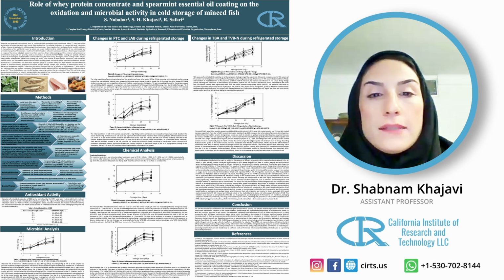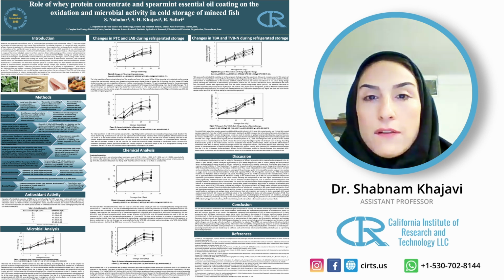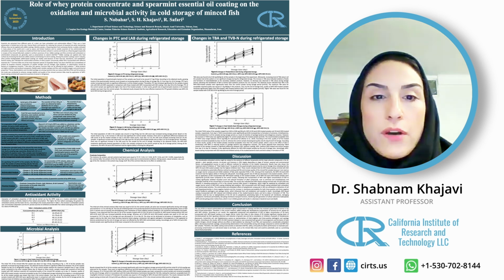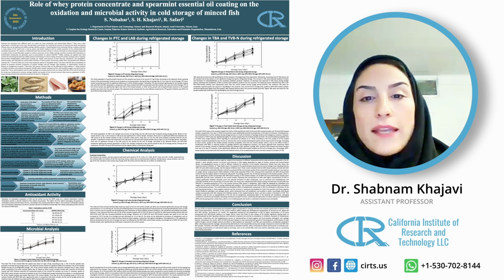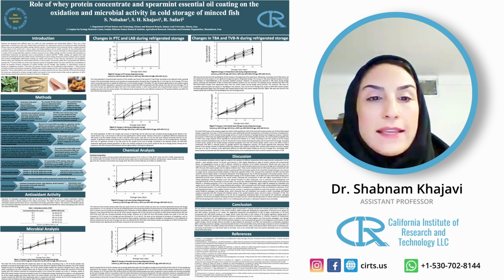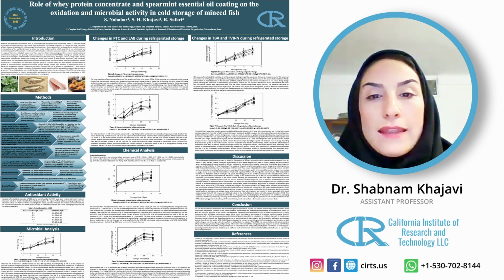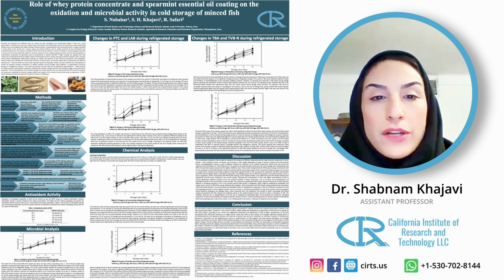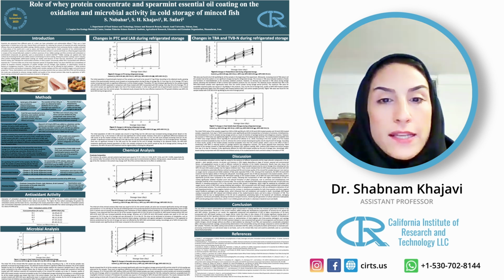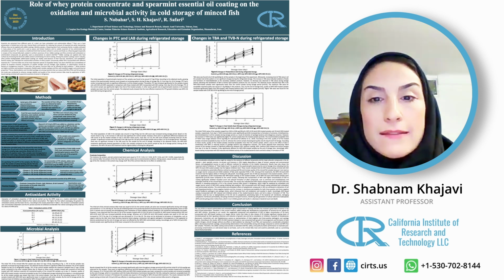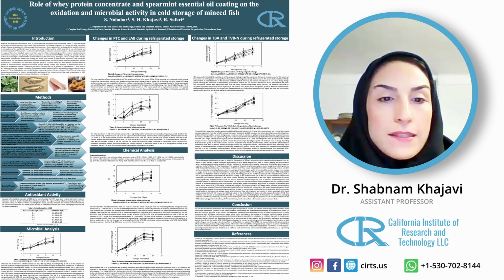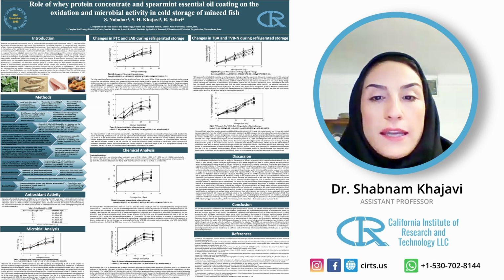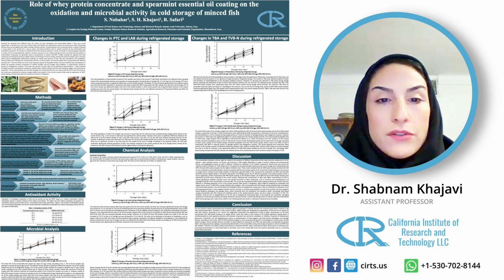According to our results, the oxygenated compounds and polyphenols of spearmint essential oil at the higher concentration of 1% weight per volume, incorporated with the whey protein-based coating as an oxygen barrier matrix that helps slow release of the essential oil, showed significant slowing down of microbial growth by lag phase extension and reduction of growth rate, and led to retardation or inhibition of growth of Pseudomonas fluorescens, Escherichia coli, and Staphylococcus aureus as representatives of gram-negative and gram-positive pathogenic and spoilage bacteria.